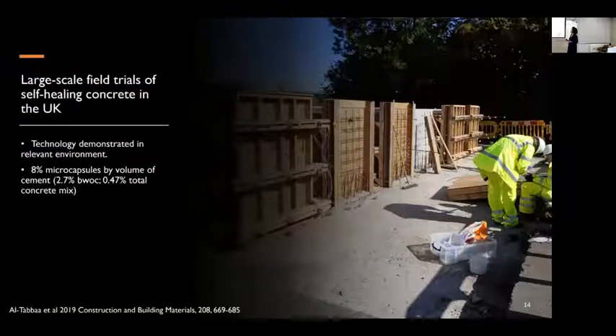So after the capsules were tested in the laboratory, we thought about testing them at a larger scale in field trials. That happened by encapsulating 8% microcapsules by volume of cement, and producing slabs with microcapsules being cast.